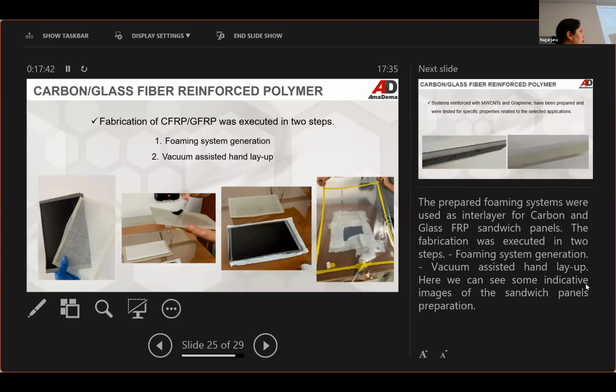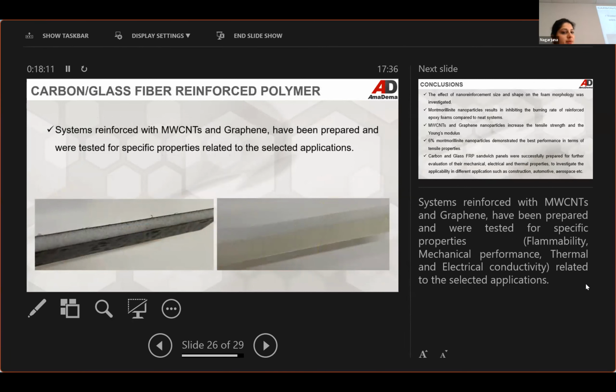Once this is solidified, you incorporate it as a core material within face sheets made of technical fabrics. And here you can see the carbon fabric and the glass fabric. The methodology we've used to incorporate this is something very well known to the industry of fiber reinforced polymers. This was the vacuum assisted hand layup. So basically you cure this under vacuum.